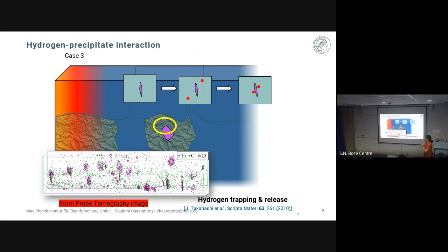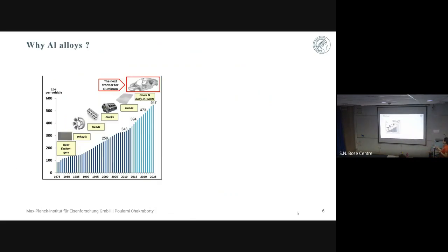So whenever you are trying to measure the hydrogen content, there is sometimes hydrogen in the atmosphere, and therefore you cannot differentiate. It is difficult to differentiate the composition in the experimental atmosphere and in the sample. So if you take deuterium, you can differentiate it because of the atomic weight. Now I will come to my